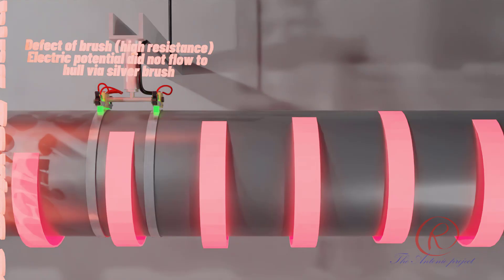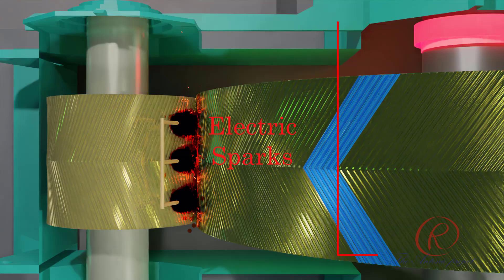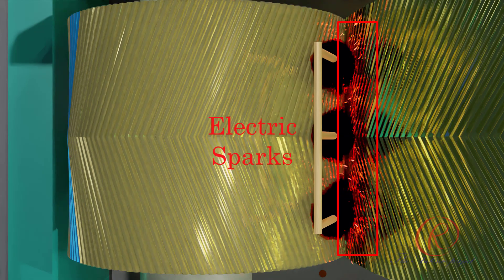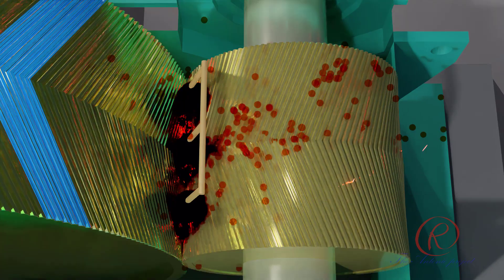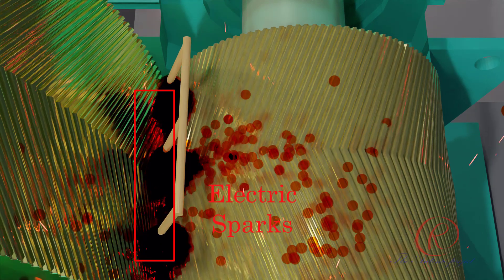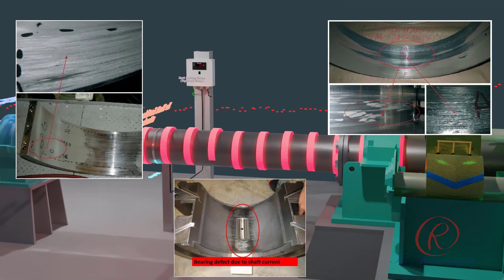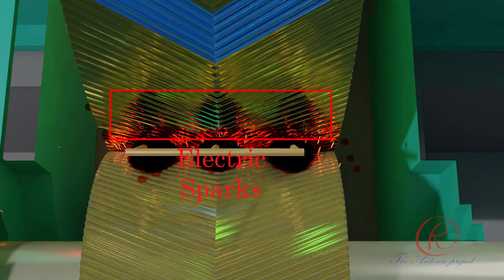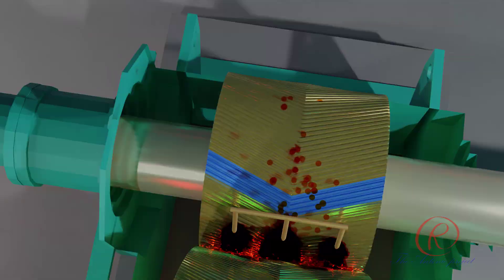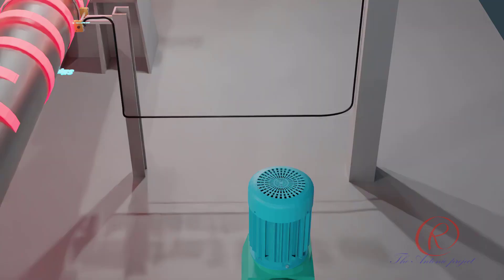An electrical potential is developed between the shaft and the hull which can cause heavy current to flow into reduction gear, main bearings and thrust bearings, and causing pitting marks. If these effects continue for a considerable amount of time, it may lead to overheating of main engine bearing caused by improper lubrication resulted by cavities from spark erosion. It may also lead to formation of oil mist, emergency shutdown of the engine, or in extreme cases, crankcase explosion.